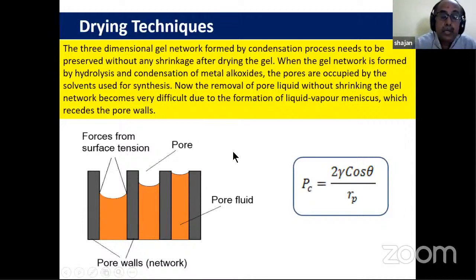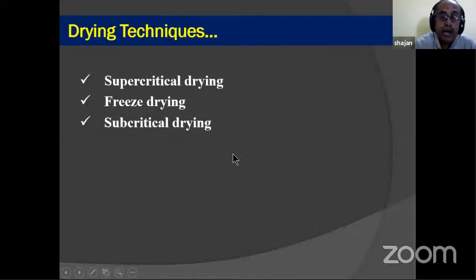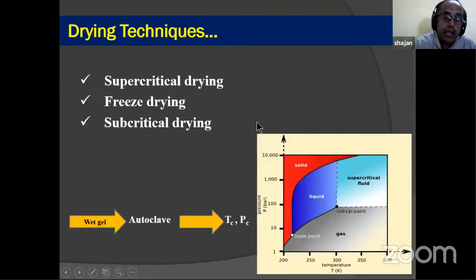Now, how are we doing it? That is a very important thing that we have to do. There are three drying technique methods available. One is called supercritical drying, another one you call freeze drying, and another one you call subcritical drying. In supercritical drying, you take that wet gel, put it into an autoclave, and you increase the temperature and pressure to its critical point. That is critical temperature and critical pressure, normally very high.